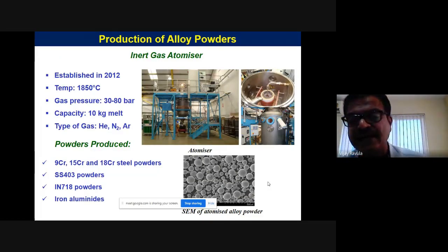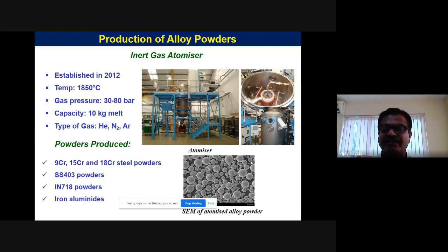And we also have a state-of-the-art facility for the manufacture of the powders. And this is an inert gas atomizer. It has three compartments. The top portion, you can see, is an induction melting furnace, where in this crucible you put your material and then you melt it. And in the bottom of that is an atomization die, where you have a metal flowing nozzle